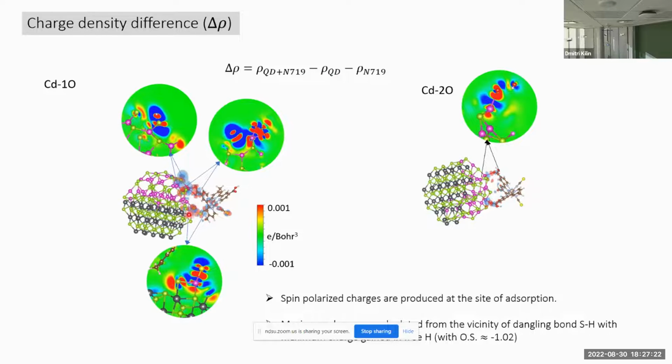Yes, so this is the 3D isosurface plot. And I took some 2D slices from the adsorbed positions of the isolated hydrogen and two oxygens and the cadmium plane, and from another plane for the sulfur and the cadmium, and we can see the negative charge on this isolated hydrogen. Red is the charge gain, and charge gain is a negative oxidation state. And blue is charge lost, and charge lost is a positive oxidation state.